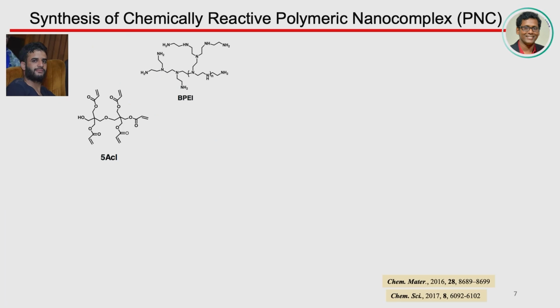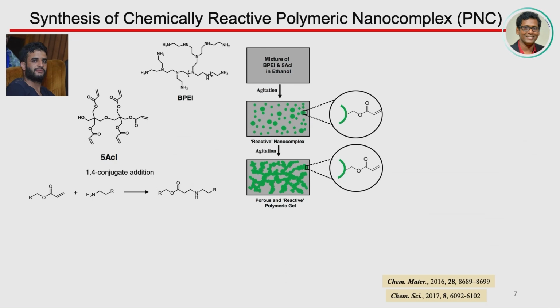So our journey started with these two simple molecules which are commercially available. This is the pentaacrylate, and this is a branched polyethylenimine, where the amine groups are on the periphery, with a much higher density. Now, you allow them to react at certain reaction compositions through this 1,4 conjugate addition reaction. What will happen? It will basically give you this beta amino ester type of linkage without producing any kind of side product. So you don't have to really think about how to separate out some side product, which is often a problem when you are thinking about some sort of chemical synthesis, right? So I like this particular chemistry because it is very simple to pursue at ambient conditions, and it doesn't really give any kind of side product.